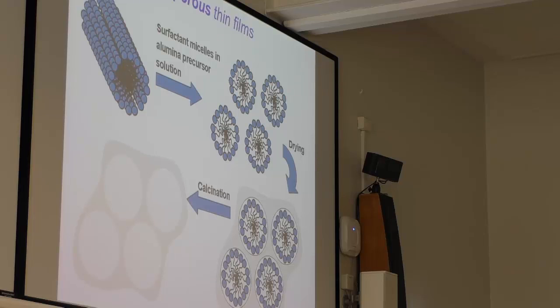In the next part of my talk, I will briefly go through a little bit of GISAXS and mesoporous thin films. So the technique is roughly similar to the one that I already described to you, at least conceptually. The difference is that we will now be looking at somewhat larger structures, right? So instead of looking at Bragg peaks that are originating from molecular or atomic planes, we will now be looking at pores or micelles, right? So they are typically an order of magnitude bigger. And this means that we need to put the detector farther away to be able to catch smaller scattering angles with some resolution.